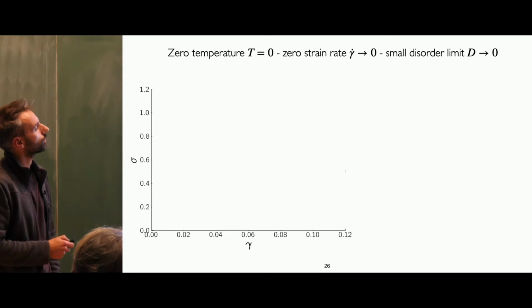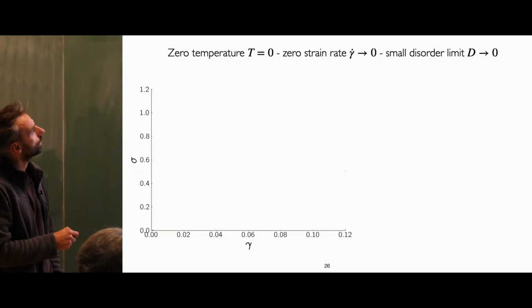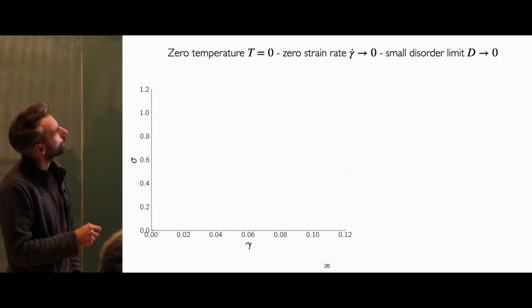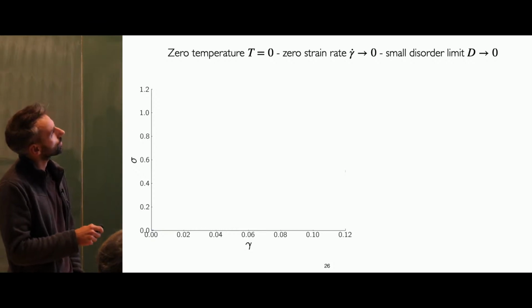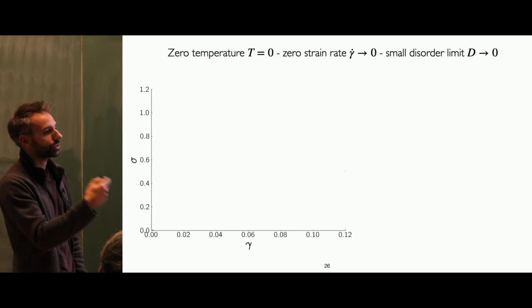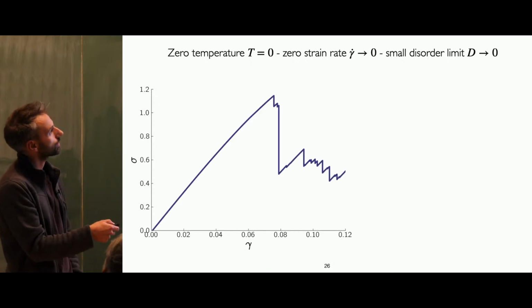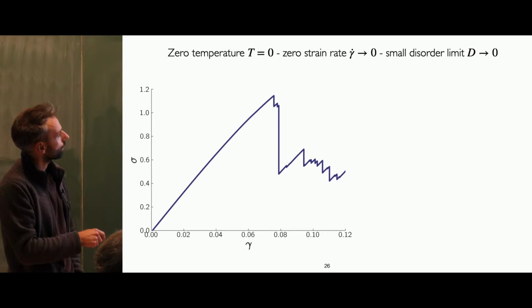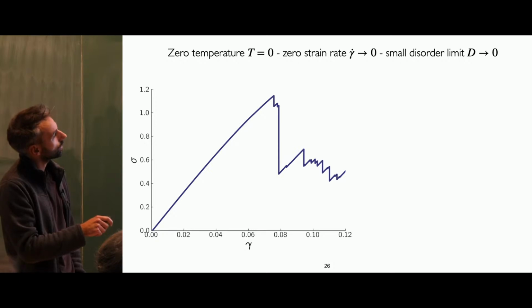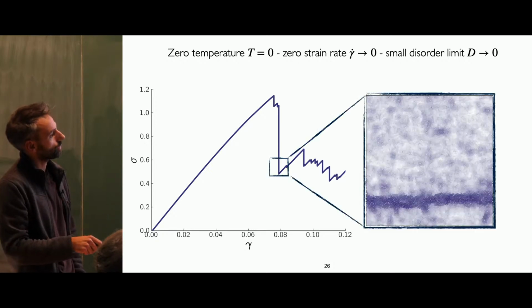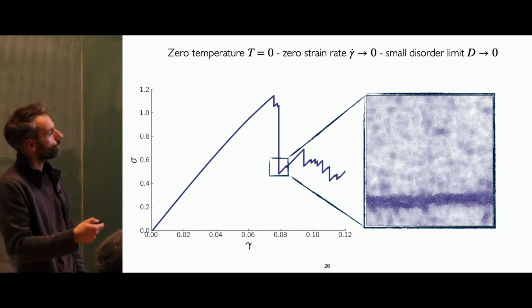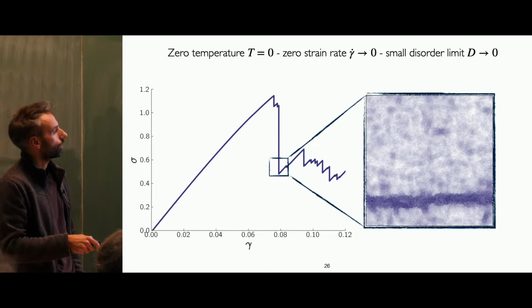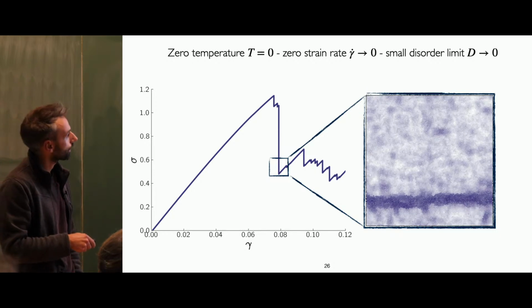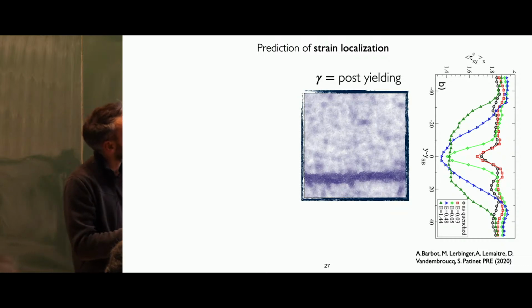So just one application of that. One thing that we looked at before was one limit: can we look at zero temperature and zero strain rate, so in athermal quasi-static yielding, and one limit will be the small disorder that you can achieve with swap Monte Carlo. In this limit it's interesting because you can go all the way to yielding without plasticity and then yield and form, for example, strain localization. And so one question in terms of prediction was, can you predict where the shear band will occur from the as-quenched structure? Some people have already looked at this, for example, for the local yield stress.